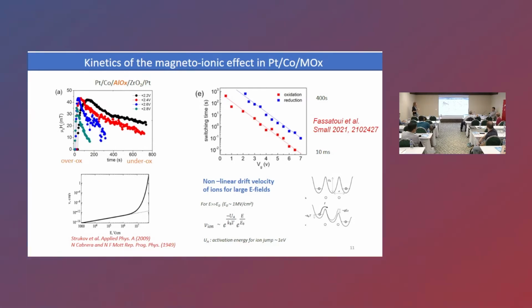So as you can see here, for example in the case of the oxidation, by increasing the applied gate voltage you can change the switching time by 5 orders of magnitude. So we start with 1 volt, we have 400 seconds to switch the magnetization. If we go up to 6.5 volts, we can go down to 10 milliseconds.